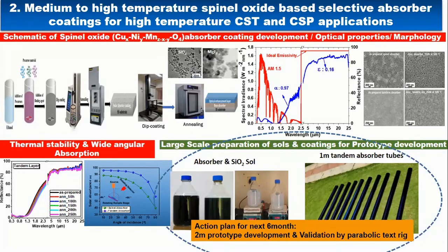Coming to the second technology, a medium to high temperature receiver tube technology for high temperature industrial process heat and power plant application. This technology is very unique, and the material we have developed is made in a very unique way. We have developed a novel spinel oxide, which has high stability up to 700 degrees, a nanostructure based spinel oxide type of coating developed for high temperature application.